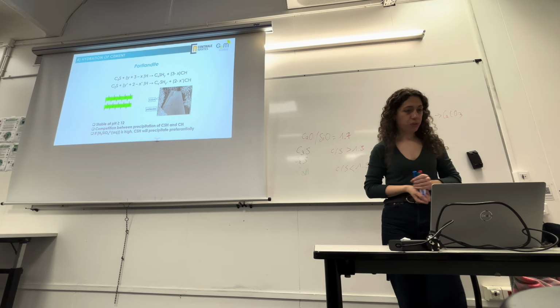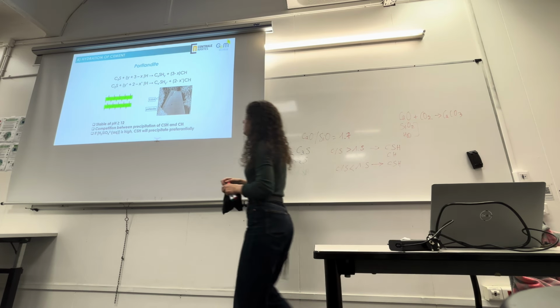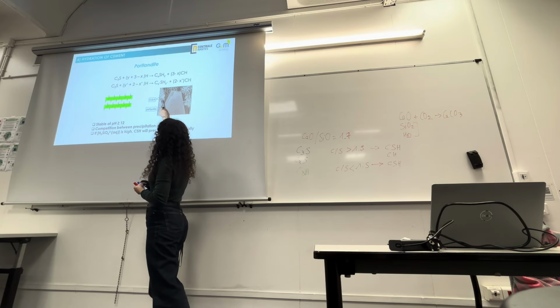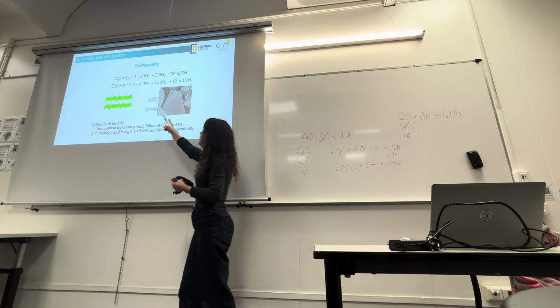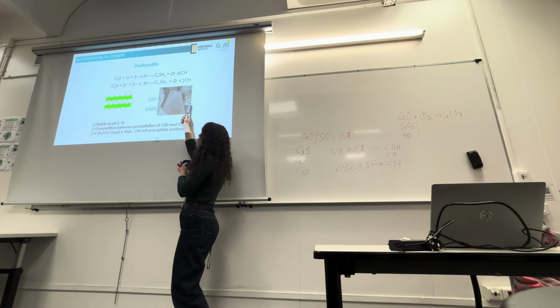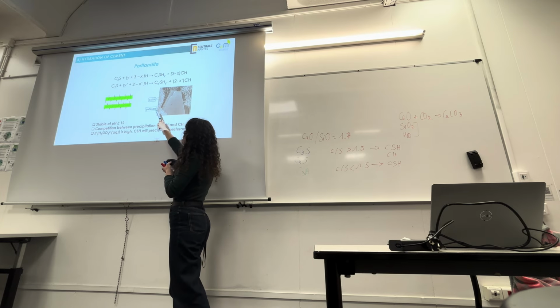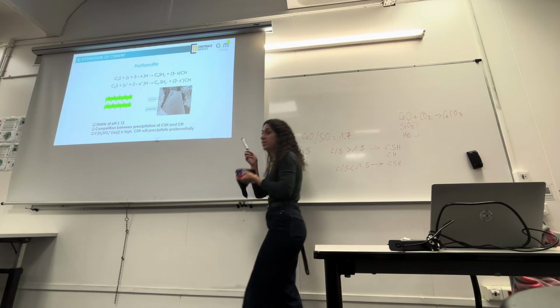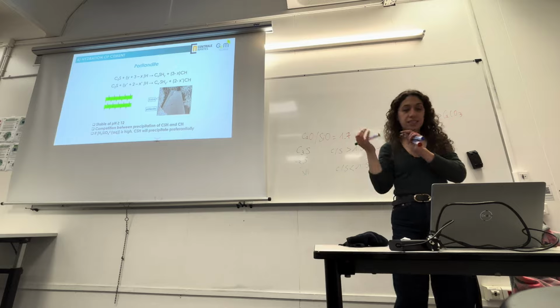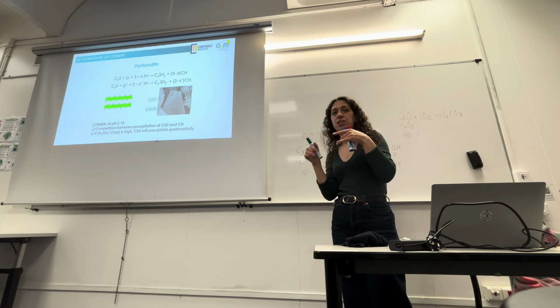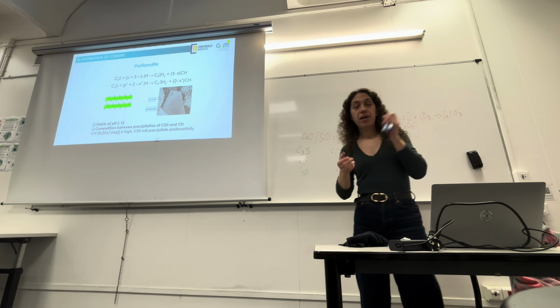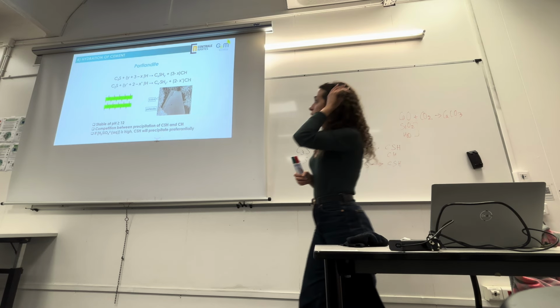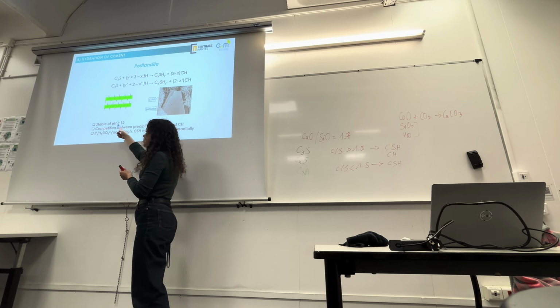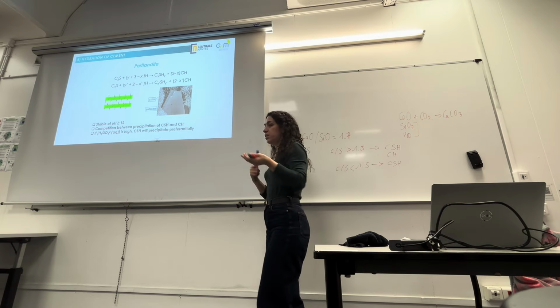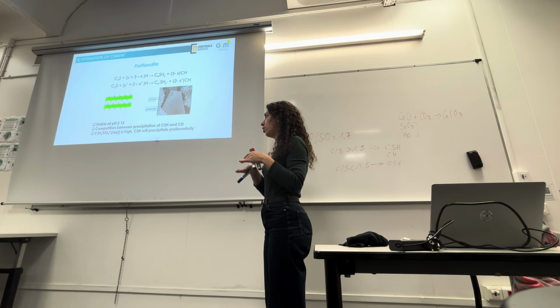Okay, now let's talk about portlandite. Here it's a very beautiful image. You can see the amorphous CSH and the crystalline portlandite. You see clearly the difference between amorphous compounds and very crystalline compounds. Portlandite is the opposite of CSH. CSH is not crystallized at all, it is very amorphous. And portlandite is the opposite, it is very, very well crystallized. So, portlandite is stable, as I said before, at a pH above 12.